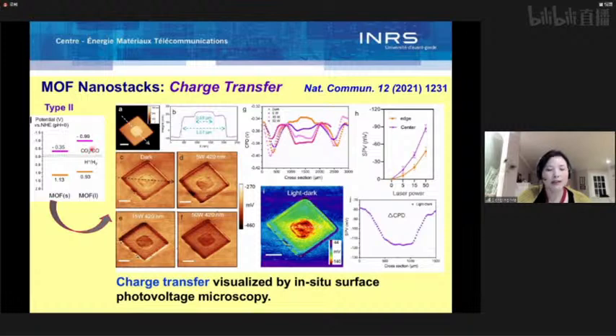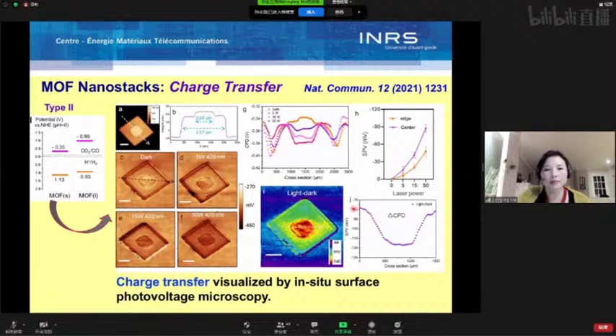top and bottom nanoplates. I will not go into details, but we visualized the charge transfer between the top and the bottom plates by using in situ surface photovoltage microscopy. Basically, we measured the contact potential difference with AFM in the dark and also under illumination with a 400 nanometer LED at different intensities. Then we plotted the contact potential difference for the center part and for the edge part. We can see the surface photovoltage is much higher in the center part.